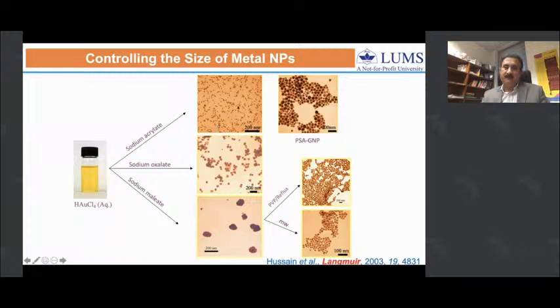Especially this sodium acrylate method is really a very good method to control the size of these particles from 10 to 15 nanometers. They are very similar to the citrate reduction method, but the particles formed by acrylate reduction are much more stable than those formed by citrate reduction method.